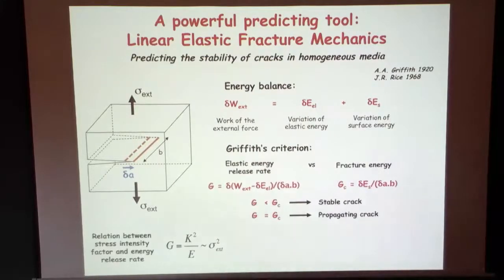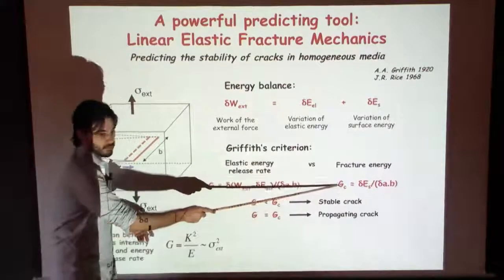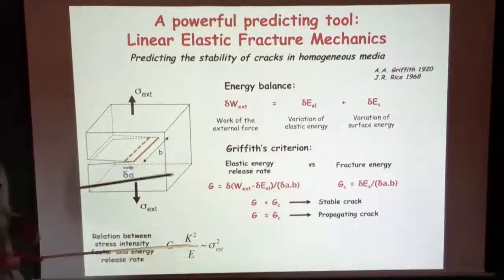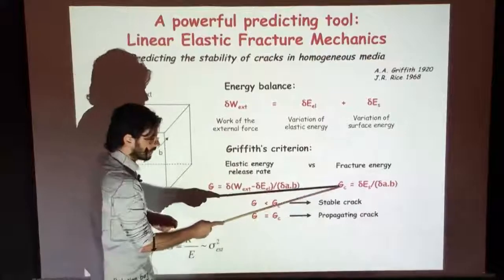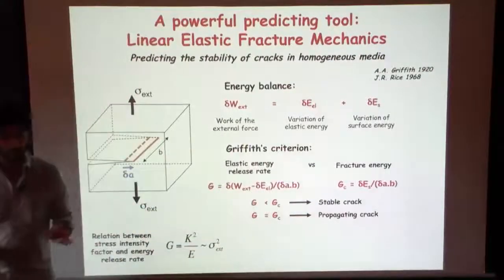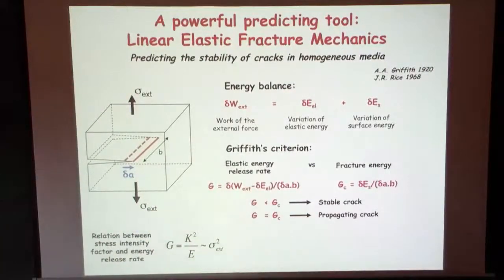Also, if you compare this term to the actual surface energy, recently there has been this beautiful measurement showing that in a perfect crystal of silicon, you can have GC actually equal to the surface energy. But this is the exception. The general case is several times to several tens of times larger than the surface energy. For metals, it's 300 times, and for polymers, it's 3,000.